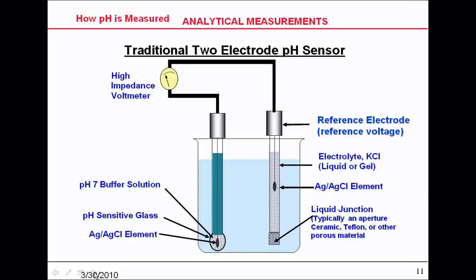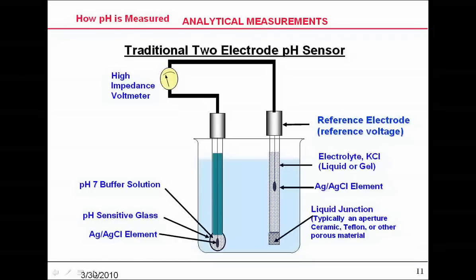finishing the bridge. In both cases, the body coming down on either side is structurally strong, but on the glass electrode, the glass at the very end is very thin and is not only glass, but actually has, let's call it a membrane on it with some oxides, because glass being an insulator would have a hard time, if not impossible, generating a millivolt transfer through it to go up that wire. So the membrane on the end of that glass is very fragile. I've seen people use corduroy pants or a knife or sandpaper to get dirt off of them, and not only are you cleaning them, but you're also damaging that membrane. So it's important to know that the reference electrode is trying to maintain a constant potential, constant millivoltage, while the glass is developing differences based on the hydrogen and hydroxyl ion activity in that solution.